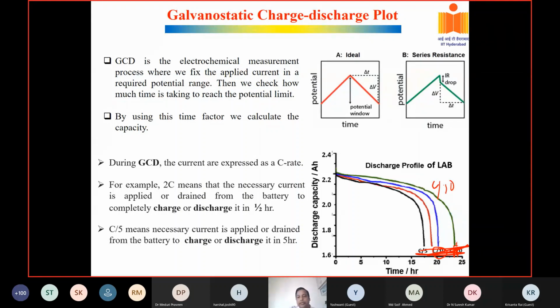At this voltage, the nominal cell voltage you can see here is around 2.1 volt or so. This is the region where it can operate, and this shows the cutoff voltage. That's what I told you in the CV. After this, the polarization is complete, so you don't have to discharge further. Similarly, while charging, you don't have to go beyond this region.